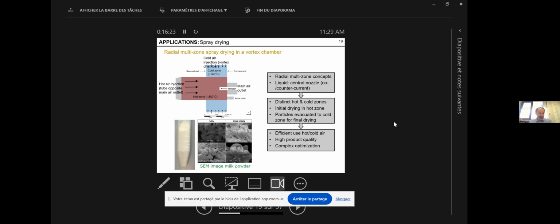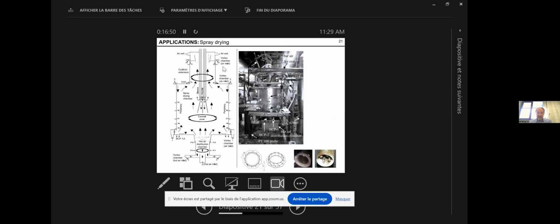Yeah. So those were the things we had to face in terms of constraints on the particle and droplet size. Then there is also energy efficiency and air use efficiency. In order to minimize the air consumption, we do not have a vortex chamber over the entire length anymore. We have them here at both ends, and that allows us to also control the axial motion. You can generate a centrifugal pressure difference between those sides, and that allows you to control the axial motion. So this is what we did in this large-scale pilot plant.